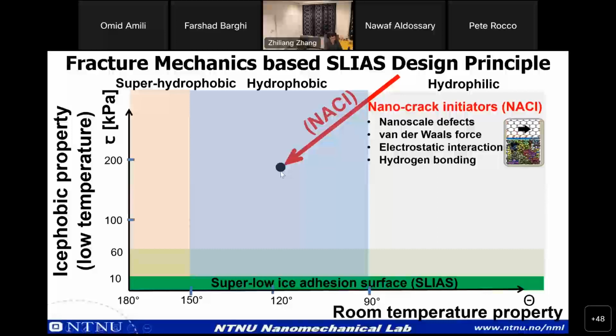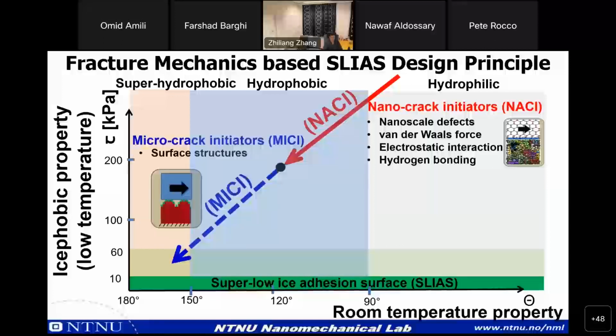If you want to go any further, for example, if you want to go down to the low ice adhesion region or super low ice adhesion region, you have to use the so-called micro crack initiator. That means you have to texture your surface, build the surface structures, such that, for example, when ice forms, we have air trapped at this roughness. So here we have a micro crack. This will function as the micro crack initiator. We call this MICI.